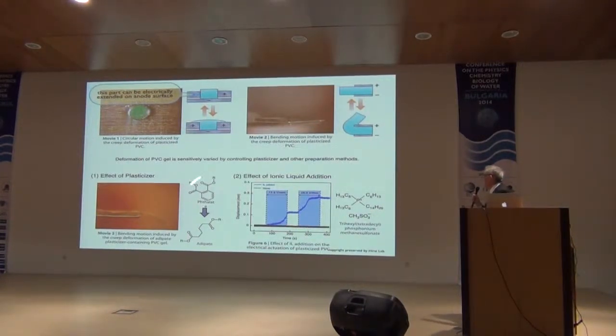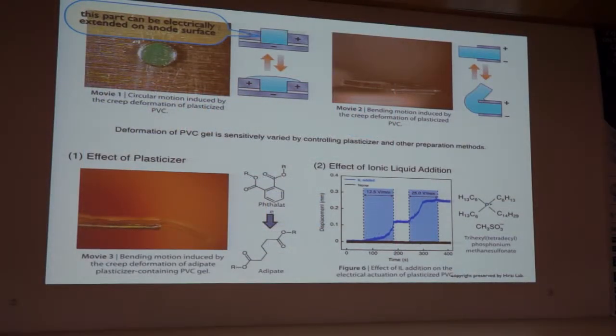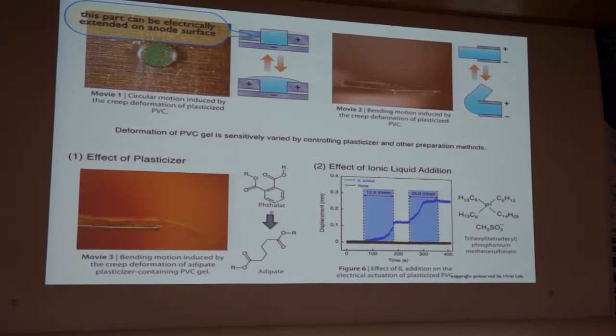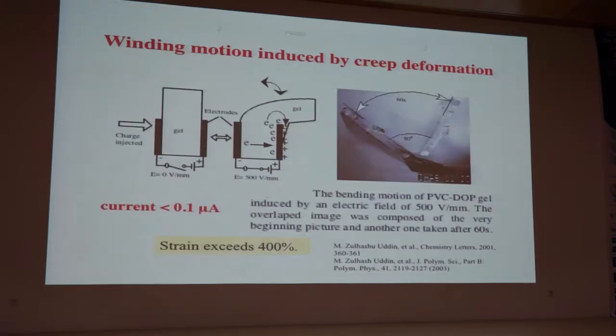When we introduce this deformation, the thickness is 200 micrometers, and the applied voltage is a couple of hundred volts, still high. To reduce the voltage, we can use an electrolyte. But as can be expected, the electrolyte permits current flow. So the energy dissipation and heat generation are huge, not convenient for practical application, though the applied voltage can go down.